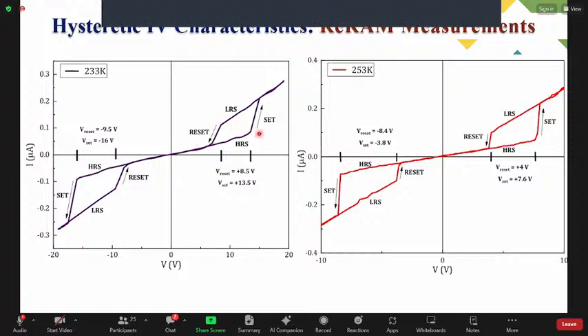The set and reset voltage are calculated for forward bias and reverse bias both, which can be seen on the screen. Now, if we increase the temperature, we can see that the set and reset voltage getting decreased towards the origin. So if set and reset voltage is getting decreased, and window is also getting better and better with increasing temperature. The current value, if we observe, the current value is getting decreased.